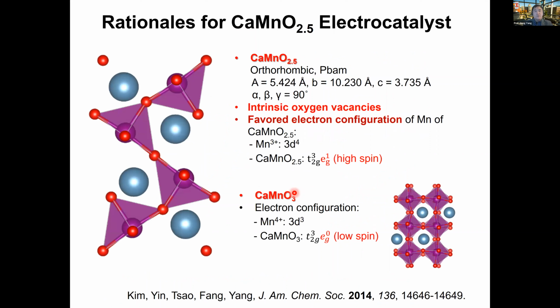So we did a little bit more careful consideration. What intrinsically makes this catalyst better than the perovskite, i.e. the O3 catalyst phase? Of course, there is oxygen defect, so there are sites being opened up. So there will be the intrinsic lattice oxygen vacancy that is favored. For the electronic configuration of the cation, i.e. the B-site metal, the change of oxygen also leads to the change of the cation center as well. For instance, in this case, if it's 2.5, i.e. the A2B2O5 structure, we can have the so-called high spin state, i.e. the eg orbital will be single occupancy.